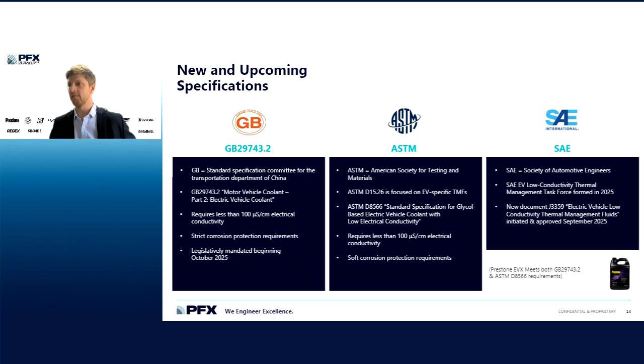ASTM is another organization very active in automotive coolants. So ASTM D15, and ASTM D15.26 specifically, is the subgroup focused on electric vehicle specific thermal management fluids. There is an existing standard out of ASTM for glycol-based electric vehicle coolants. This is ASTM D8566. Admittedly, this is a softer standard compared to the GB standard. It still requires less than 100 microsiemens of electrical conductivity, but the corrosion testing requirements are not up to the same level of scrutiny as the GB test.